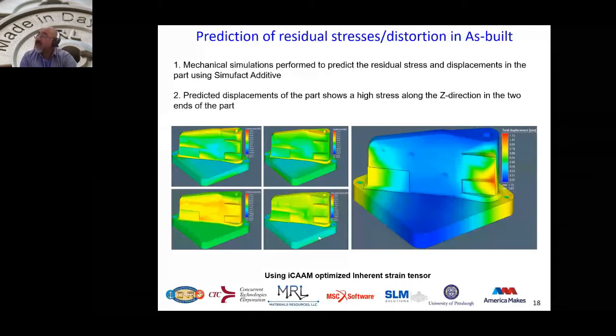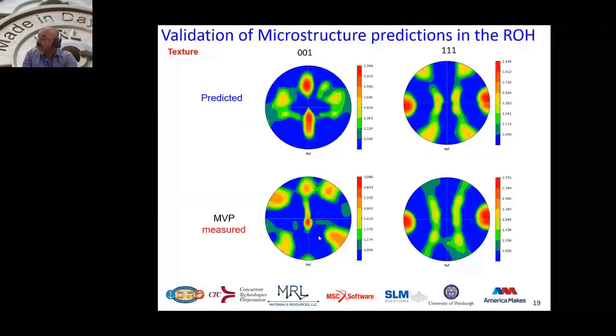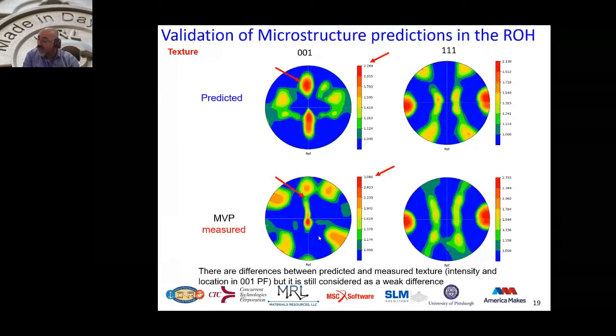Some of the things to show during the blind testing is comparing the texture in the critical region of homogeneity, the predicted texture to the measured texture using the samples that were identified in the earlier slides. And you can see we are pretty close when comparing the prediction and the measurements. Since we utilize the orientation distribution function, we are able to do the comparison quantitatively, not just qualitatively. Similar location on the 111 pole figure, very comparable intensities, small variation in the 001 pole figures, but the intensities are comparable and within the expected variability of the experimental texture measurements. These are the areas that we are highlighting in the slides here, and for both of them it is still considered a very weak texture.